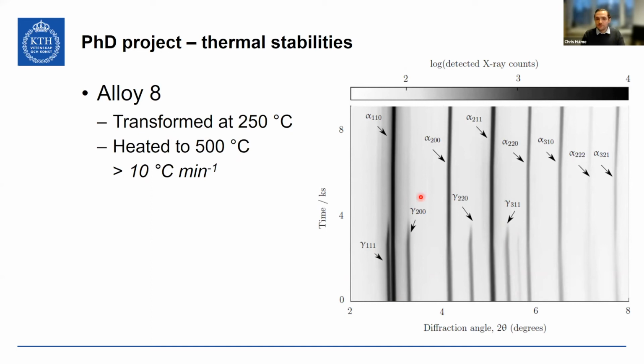So what we can see is that at short times, when the sample is just heating from room temperature, everything gets lower diffraction angle, lower Bragg angle, which means the lattice is expanding, its thermal expansion, as we'd expect. Then very abruptly, the austenite shifts. It kind of turns a corner. You can see that especially on the 220 peak here, it turns a corner and goes to higher diffraction angles as the lattice is contracting again because of the loss of carbon.